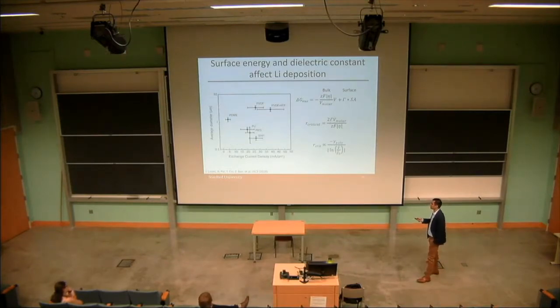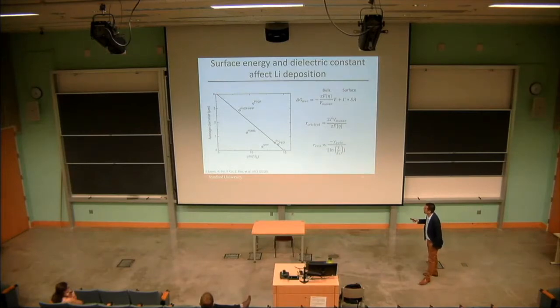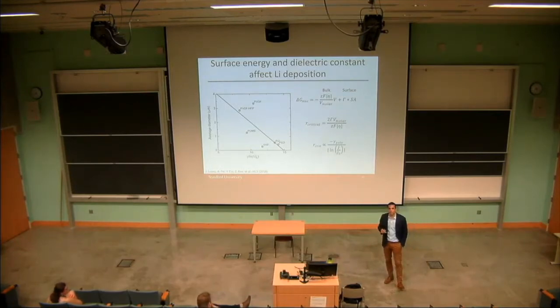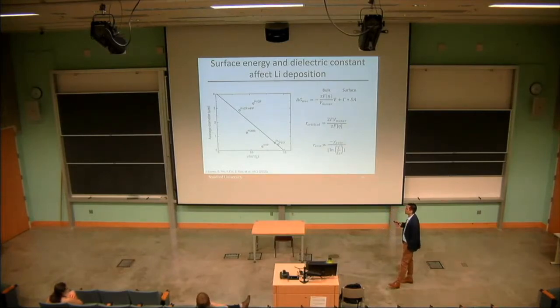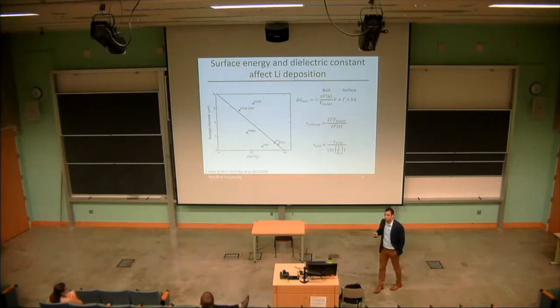But again, when we look at just the exchange current density versus the diameter, we can see some clustering, but there's no real clear trend here between these different systems. But maybe you're saying, well, you wouldn't expect that because they're competitive with each other. So you have surface energy in the numerator and then exchange current down here in the denominator. So when we do look at this parameter, there is a bit of a linear trend. And so what we believe we found now is these two descriptors for these polymer coatings. So you can have something that has a very low surface energy and a very high dielectric constant or high exchange current that will then give you larger diameter lithium morphology that then leads to better cycling.